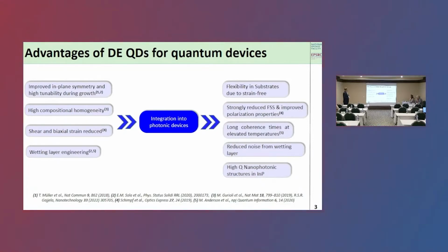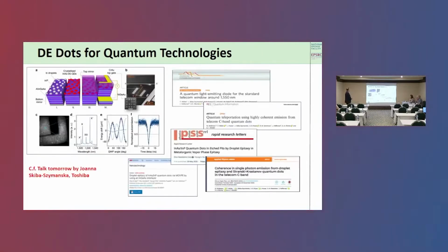The fine structure splitting and the symmetry of the dots appear to be better at 1550 than with the Stranski-Krastanov method. And this has led to long coherence times, and there is reduced noise. We believe there's reduced noise from the wetting layer. But also when we move to indium phosphide, we can make even better nanophotonic structures. So there are a number of advantages that translate into moving to 1550 and also to droplet epitaxy.